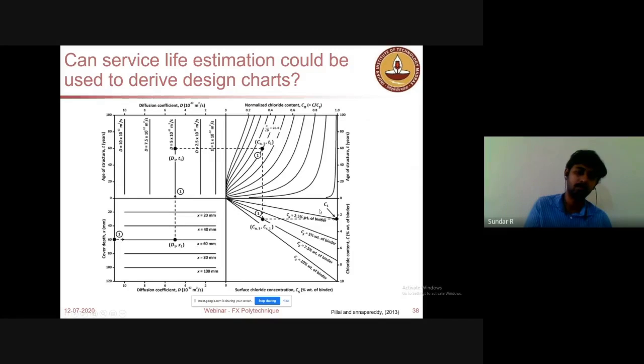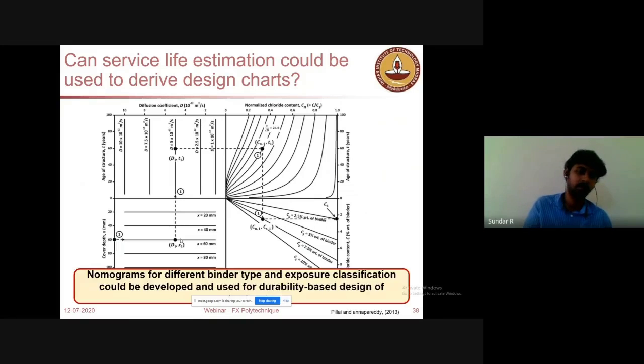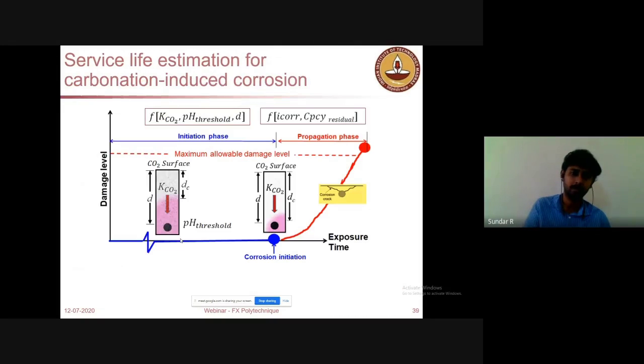So this is a nomogram. You read from here: if you have a chloride threshold as some number, and a diffusion coefficient intended as some number, you will get the necessary cover depth to achieve the intended service life. This is how we developed these nomograms based upon the service life calculations. Nomograms for different binder types and exposure classifications can be made, and those will be a very good tool for calculating the durability of a concrete structure over a period of time. So that is the design based durability.